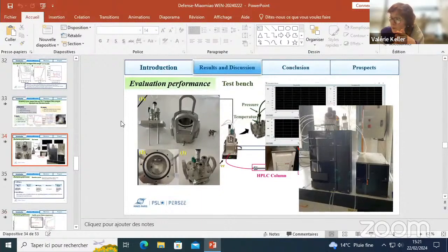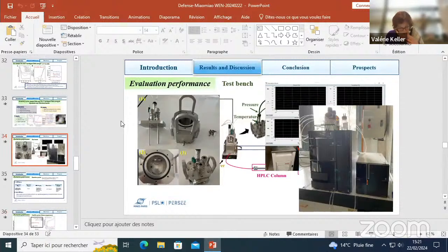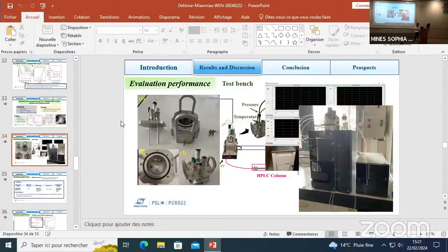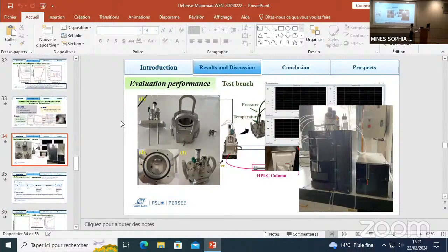This is very important because at the end of chapter 4, page 185, you are comparing different photocatalytic activity. And I think you have also written, if I remember well, that some of your photocatalysts have higher activity than the ones mentioned in literature. But it is dangerous because you cannot compare. You are not sure that you have the same experimental conditions and the same photon flux as the one mentioned in literature.